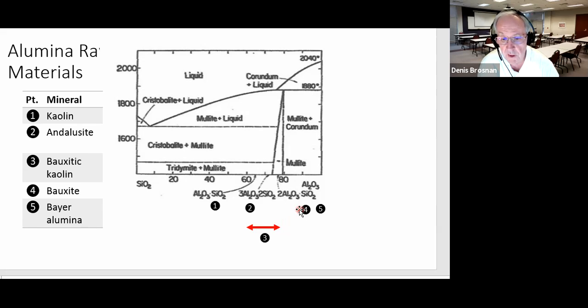If you want more alumina than that, you're going to go over here to bauxite, calcined bauxite, which occurs in many areas of the world. It has aluminum oxide or corundum crystals as its main ingredient, but typically calcined bauxite is going to be about 88% aluminum oxide. So there's 12% of something else there, a lot of silica and some iron and titanium, things of this nature. During World War II or thereabouts, the Bayer process for refining alumina was present. So very high purity aluminum oxide became available. And so that's the Bayer process aluminas that I've given here.